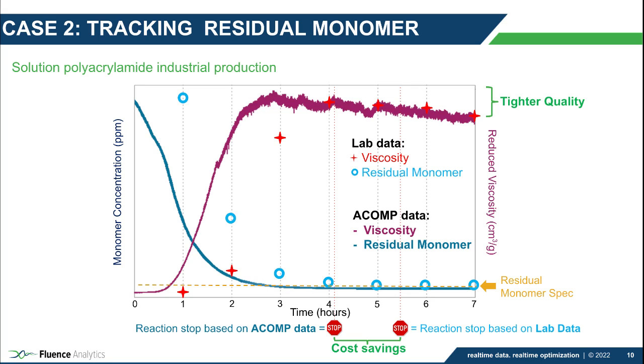Here on the plot, we can see the monomer concentration calculated from the UV measurements as it decreases exponentially throughout time as the reduced viscosity increases as the polymer chains increase. These are all indicative of the reaction progressing and monomer conversion. We can see here that from the usual method of manual extraction of aliquots followed by offline characterization, the confirmation that the minimum residual monomer threshold in parts per million has been achieved comes at least 1.5 hours after what has been detected with ACOMP. In this case, if the reaction is stopped earlier, both money and time can be saved, as no further conversion is necessary and a more consistent product quality can also be achieved.